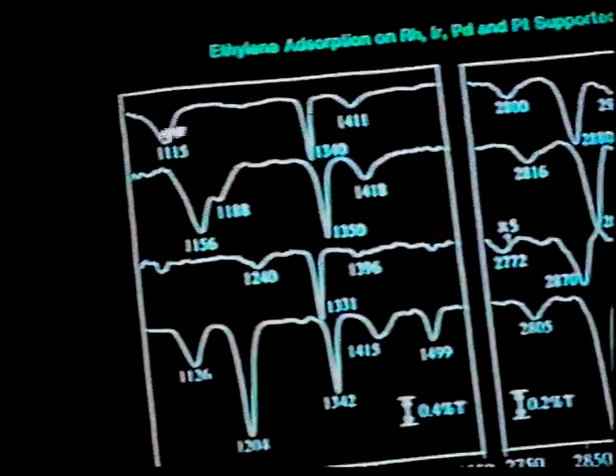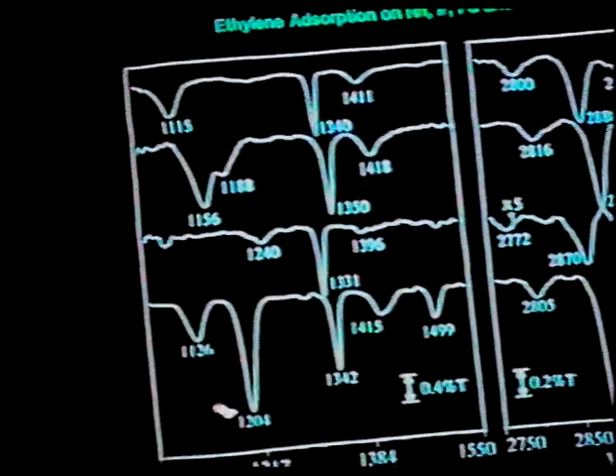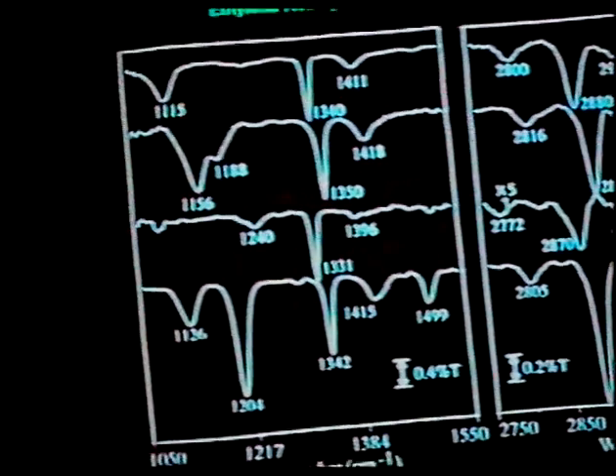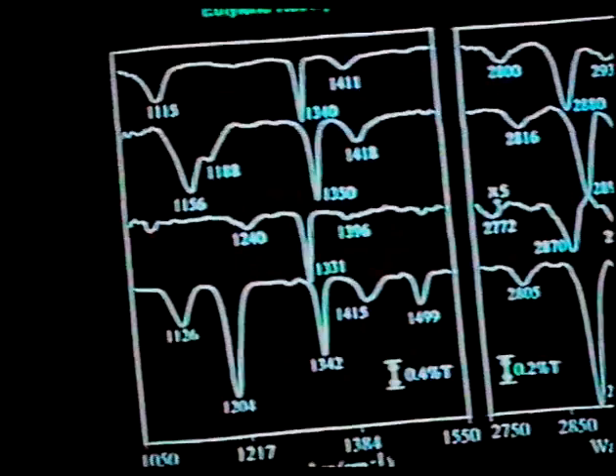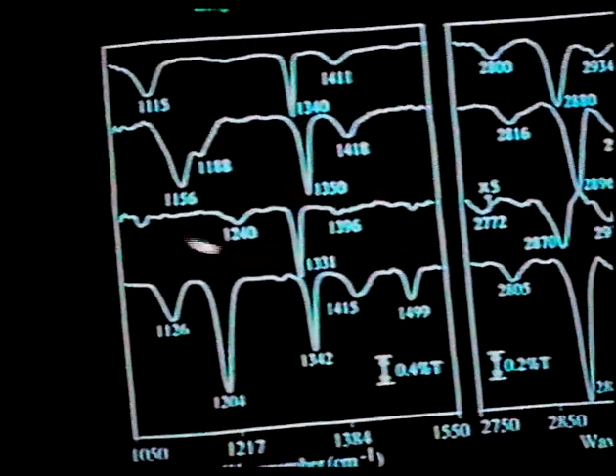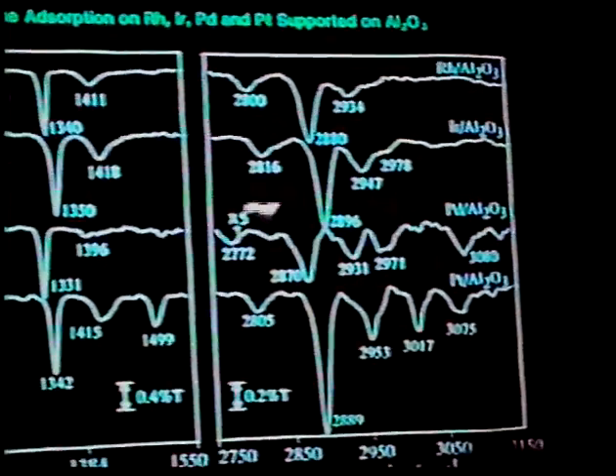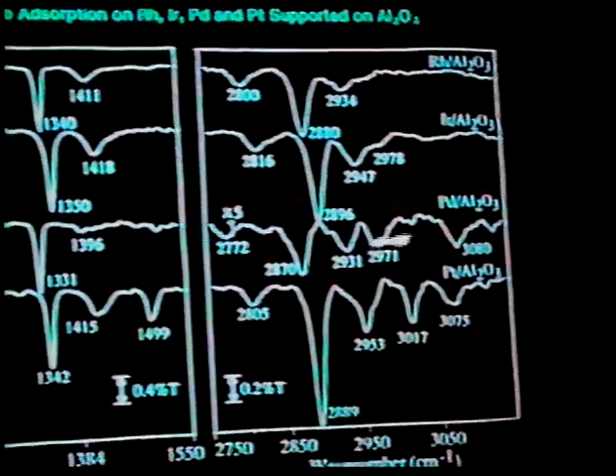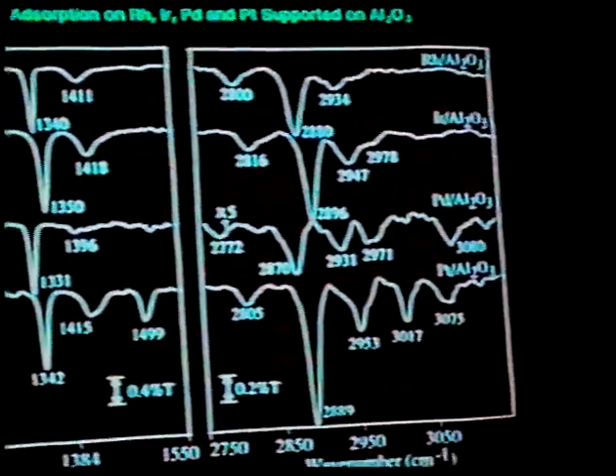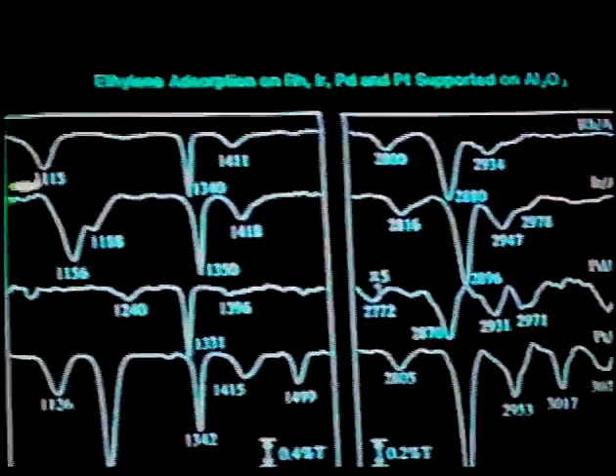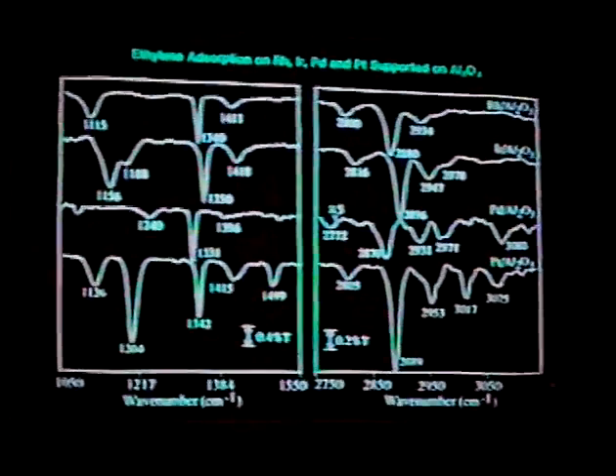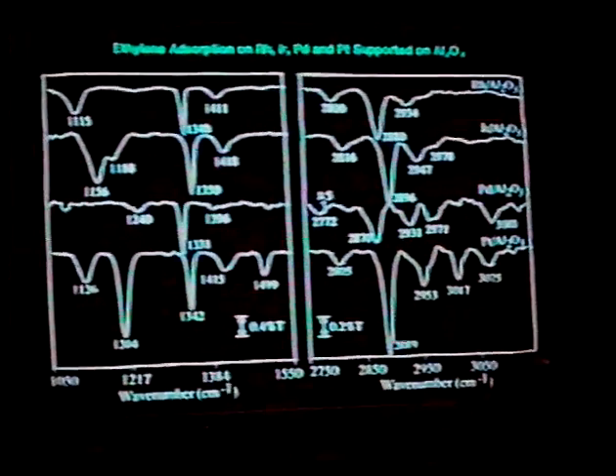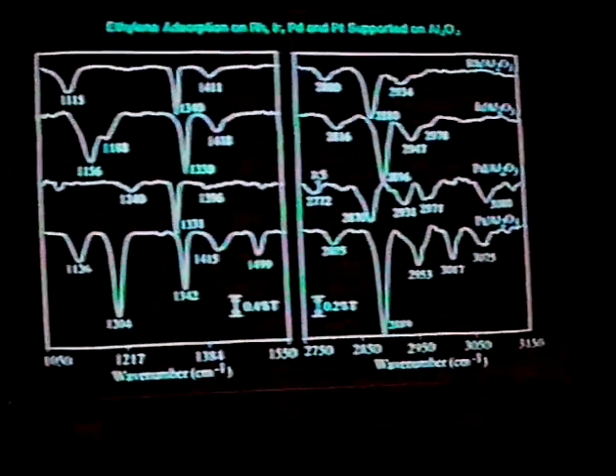What's interesting is that the relative population of the pi-bonded species is different. And not only is it different, your ability to detect it is different. Whereas the 1200 wave number band is very strong on the platinum catalyst, it's virtually absent on the palladium catalyst. However, you can see some of the CH stretchings. You'll notice that this is enhanced by a factor of 5 over the rest of these. So on palladium, we indeed do have the pi-bonded species, but for some reason their spectra are not nearly as intense. Rhodium, on the other hand, exhibits features exclusively related to the ethylene. Again, these rhodium particles are sufficiently large that you have planes, but you should also still have those sites between the planes where you might expect the pi-bonded species to form. They just do not seem to want to form on the rhodium catalyst.